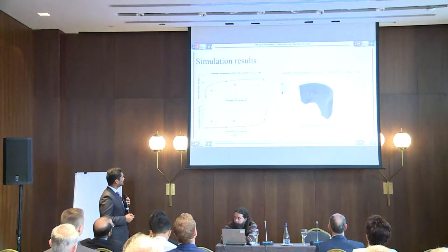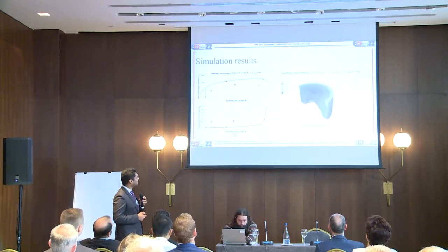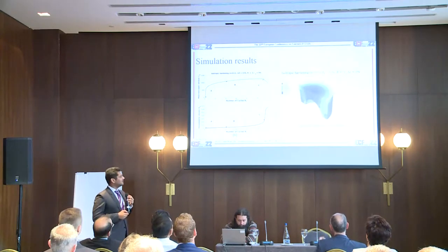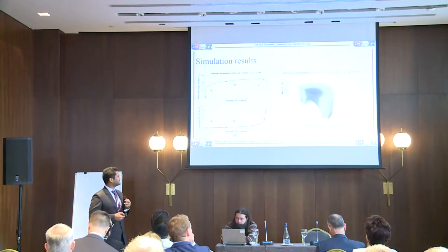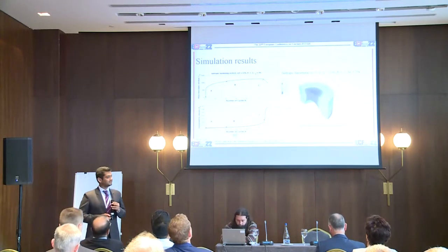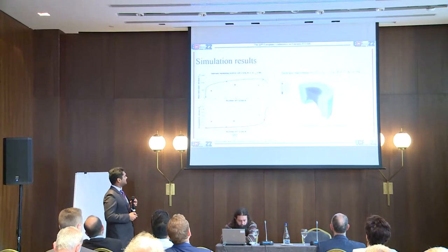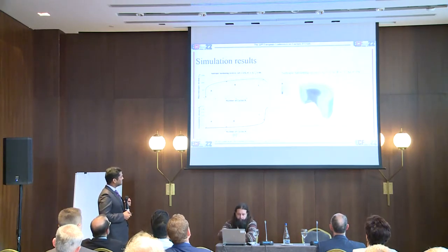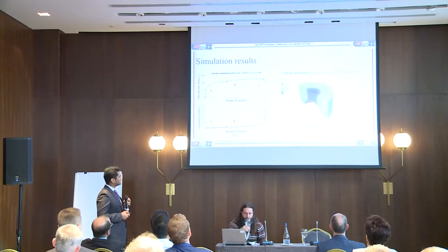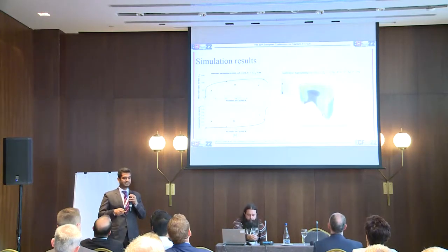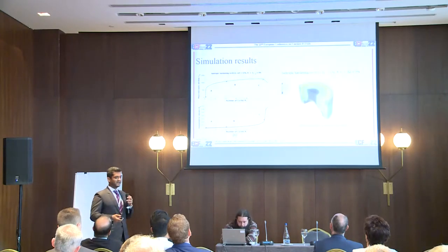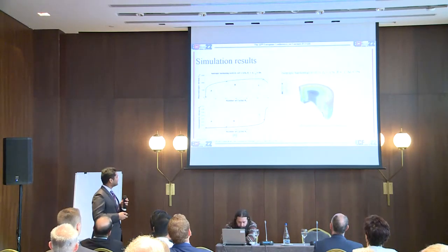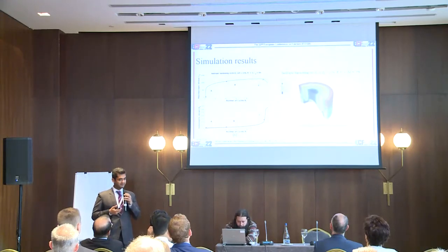Here you can see the low-cycle fatigue simulation with isotropic hardening material, initial void volume fraction of 11%, strain ratio of minus one, and applied strain amplitude of 5%. Initially the void was a sphere, but with the simulation, this void is growing and the ligament is decreasing in size. Experimentally it was shown that this material experiences cyclic necking, which leads to cyclic void coalescence, and after a while a macroscopic crack will form.